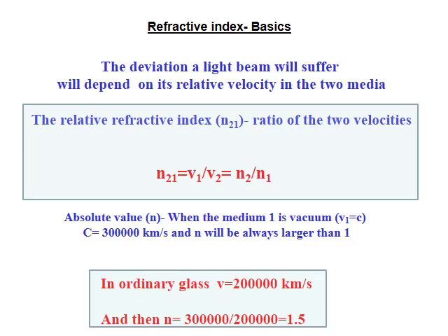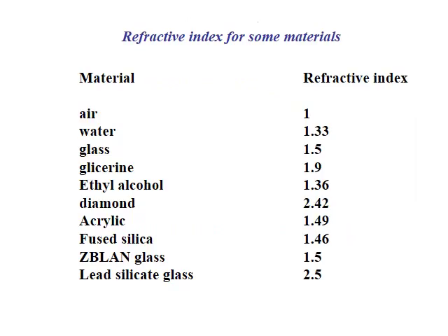The deviation a light beam will suffer will depend on its relative velocity in the two media. This defines the refractive index as the ratio of the two velocities. For example, in ordinary glass, the velocity of light is 200,000 kilometers per second. If we take the velocity of light in vacuum, this gives a refractive index of 1.5. As general information, this table gives the refractive index value for some materials we use every day.